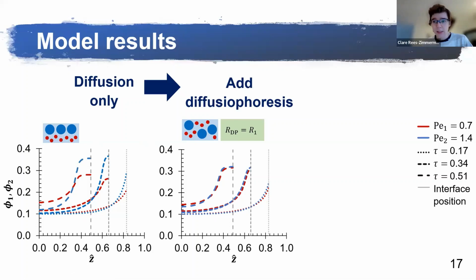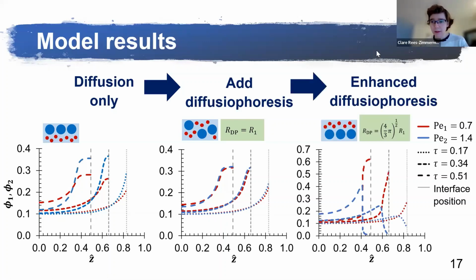So next, I add excluded volume diffusiophoresis to the model. You now see that the red and blue lines are pretty much on top of each other. So this is predicting a uniform film. It's suggesting that excluded volume diffusiophoresis is acting against large-on-top stratification. I then see what happens if I increase the excluded distance around each of the large particles. So this is strengthening excluded volume diffusiophoresis. You'll now see that at the right-hand side of the graph, the red lines are above the blue lines. This is showing a prediction of small-on-top stratification. So it's further supporting that excluded volume diffusiophoresis could be causing small-on-top stratification.